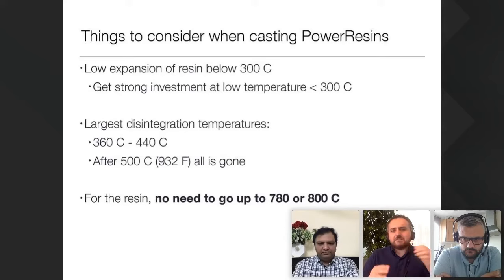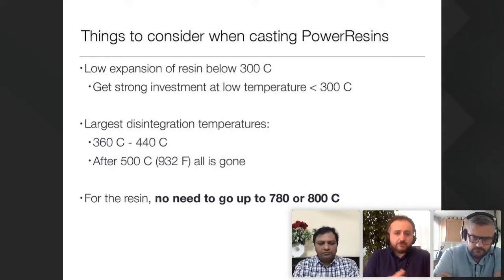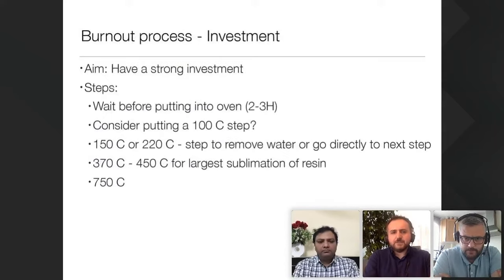And we know that the largest disintegration period is around 300 to 450 degrees, but it already starts before that. So what is important is to have strength at the low temperature, and after 500 all is gone. So we don't need to heat up the oven to 780 or 800 degrees.